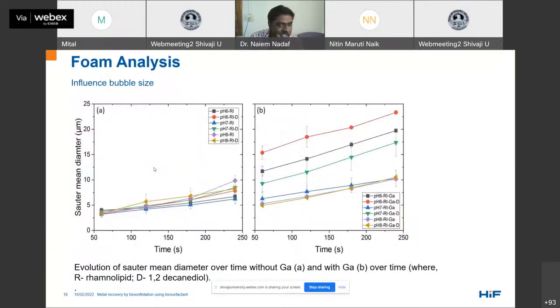So these first graphs show the influence on the bubble size, and on the left side you can see this graph represents the bubble sizes for rhamnolipid alone and rhamnolipid with decanediol, whereas on the right side it shows the influence of gallium as well as decanediol at various pH. So here we can see that small bubbles are formed without gallium, as compared to the bubble size, which keeps on increasing in the presence of gallium as well as both gallium and decanediol. And these findings relate very well with the next experiment, that is bubble shape and water content.